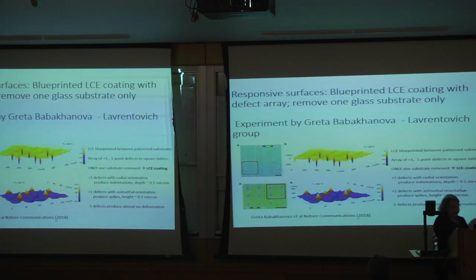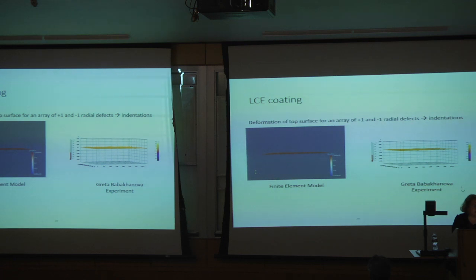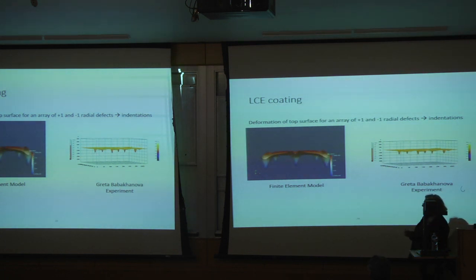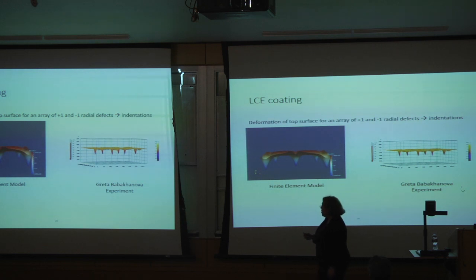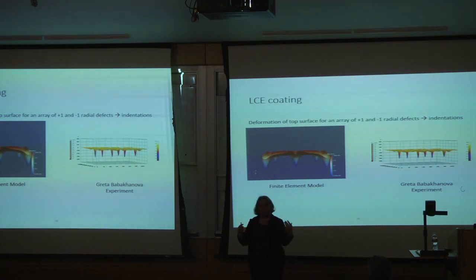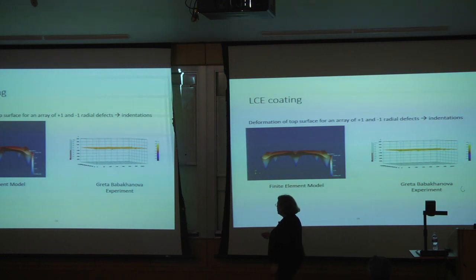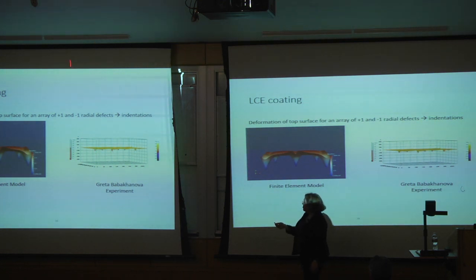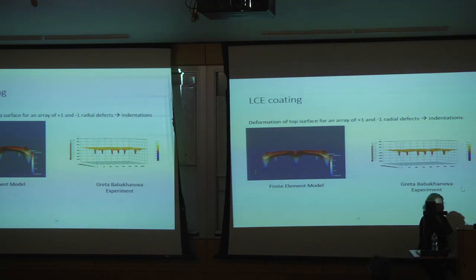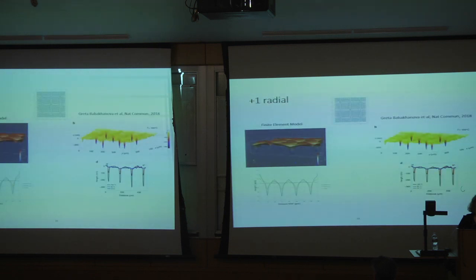Okay, so we wanted to figure out if we could understand how that happens. So here's a finite element model of the dimple case, and here's the experiment. This is just showing the shape of the top surface. So we can see how the dimples go. And we've actually also done some analytical calculations that indicate how the shape transformation should proceed as a function of temperature and the change of nematic order. So if you have plus one and minus one radial defects, you get indentations. I like to call them dimples. And that's the comparison of the plus one and minus one.